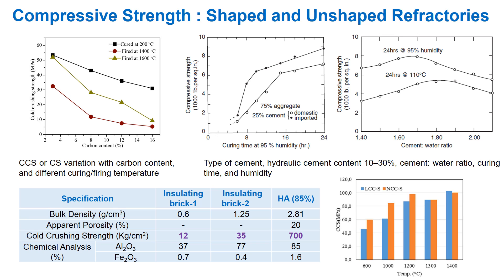Here I have tried to compile different CCS data concerning composition, processing conditions, and properties for both shaped and unshaped refractories to develop and synchronize performance analysis. For example, the influence of carbon content and temperature indicates different levels of CCS variation, as carbon has oxidation behavior and graphite has a flaky structure. Dense and porous refractories have corresponding influences on CCS. For unshaped refractories, mostly castables, strength depends on hydraulic cement content, cement-water ratio, curing time, humidity, and it varies also with respect to temperature.